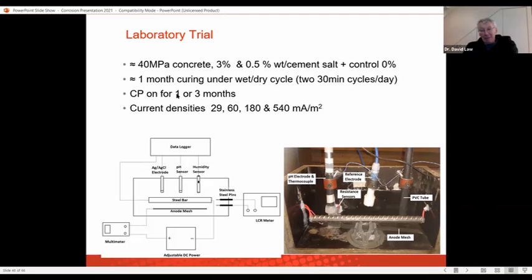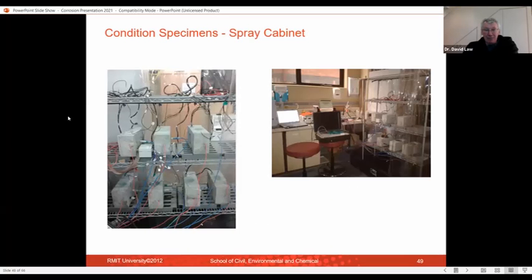Three months of 29 was equivalent to 1 month of 60 of total charge passed. So we could look at whether it was total charge, or whether the buildup of that charge over a period of time was more successful in providing any protection. These are quite short-lived specimens, so obviously they have drawbacks, but it's to give us an idea of what we might expect.